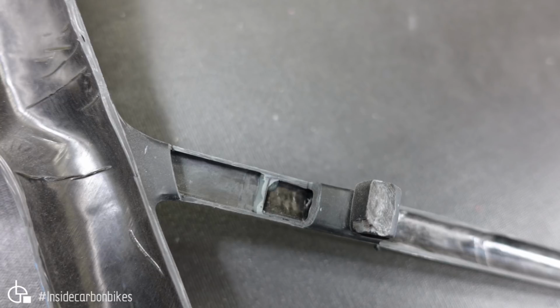And the junction of the seat stay to the seat tube, again, there's a bonded joint. You can see the adhesive excess through there, so plenty of adhesive. That all looks pretty solid. There is a small void you can see here, but that's right in the middle of it. The consequences of that are going to be very, very minor. If it was open to an edge, you're more likely to get some peel stress, but where that is, that would be acceptable. The other thing you can see is a void up on the seat tube, up the top, and you'll see that it's coincident with this crease in the bag through here and that excess resin. So there's obviously been a little bit less than ideal compaction through there, and you have a build-up of thickness of material, so more likely to get a void.